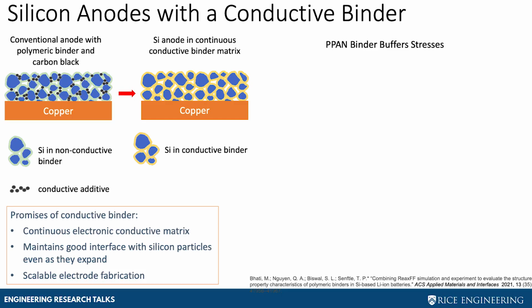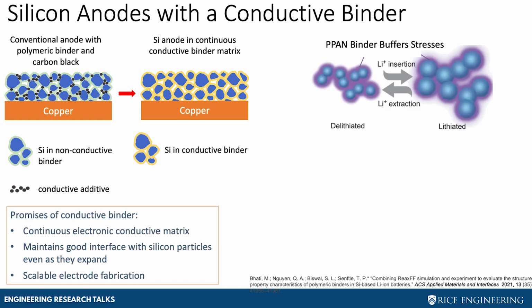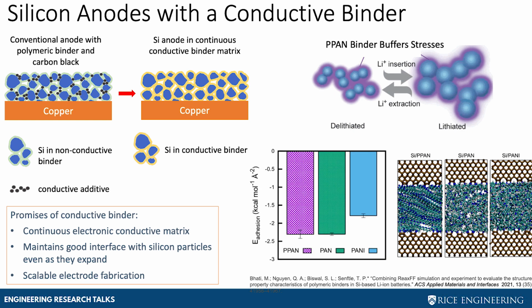So for a long time, we said, hand waving, that the polymer binder helps alleviate stress. We just said that, with this picture of swelling and expansion. Actually, with one of my colleagues here at Rice, Tom Senftle, we were able to show not only does it alleviate stress, but the pyrolyzed PAN actually has structuring that allows lithium to transport through the silicon very effectively. And because of this, we are now able to understand why the pyrolyzed PAN is such an effective binder. So now let's take a look at performance.